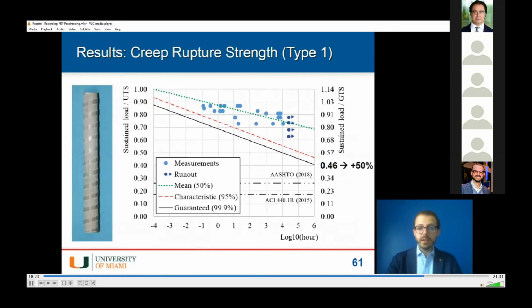And here you see our creep rupture strength prediction for the type 1 bar that you see represented on the left. You see that by simply interpolating our points, we get a strength that is at approximately 80% of the guaranteed tensile strength, reading numbers on the right side of the diagram. By accounting for statistical variability, we shift that down sensibly, and we do not intersect any of the rupture points.